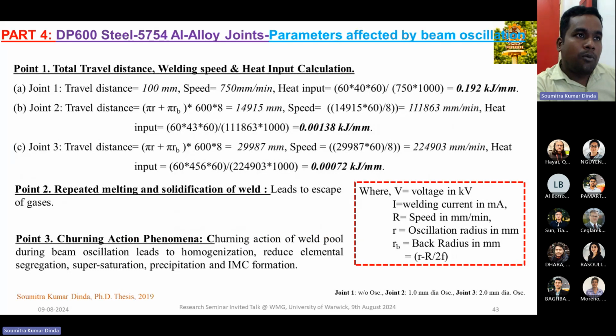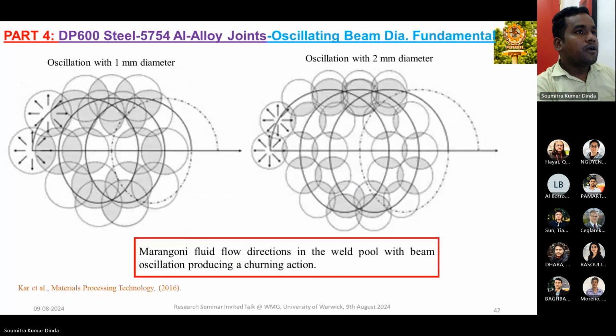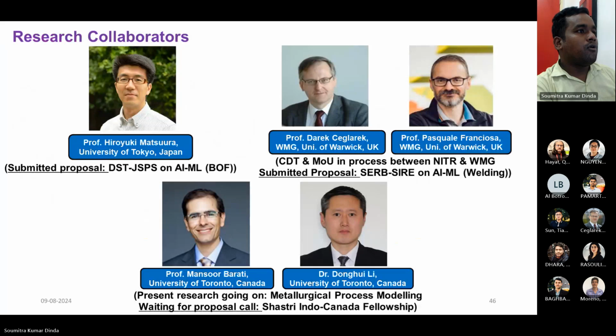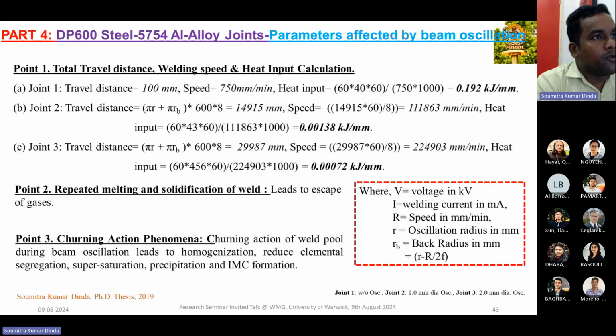But if intermetallics form, how do they grow? I missed one slide. The intermetallics formation grows according to an Arrhenius type of equation, right? So if we increase the temperature, according to the Arrhenius type of equation, your intermetallics thickness will increase. But by using the oscillating beam, we are decreasing the peak temperature and decreasing the cooling rate. That means we are decreasing the intermetallics growth phenomena. So that's why we are getting smaller intermetallics, or very less in quantity, in case of the optimized condition.